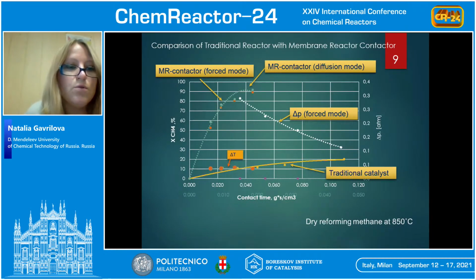First of all, it's necessary to note a comparison of two reactors with traditional catalyst and membrane catalyst under dry reforming conditions. The results you can see on the slide. Under the same conditions on catalysts of the same chemical composition, the conversion rates were compared. At the same conversion rates, the contact time on membrane and conventional catalyst differs by an order of magnitude. On a membrane catalyst, the contact time is 40 times shorter than a traditional one, that is, dry reforming in a membrane reactor proceeds at a much higher rate.